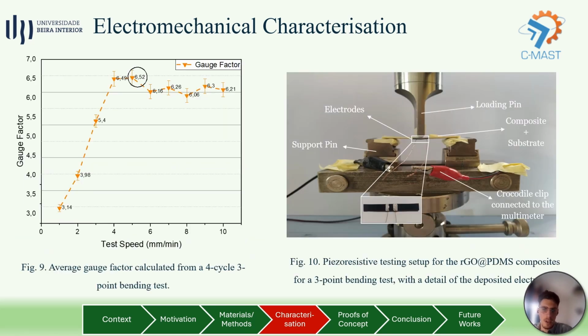We began with 3-point bending tests using the setup shown in Figure 10, and the first stage consisted of determining the best test speed, where a direct relationship with the gauge factor was observed, since speeds above 4 mm per minute always led to values above 6. However, at very high speeds, the electrical signal acquired by the multimeter was sacrificed due to its low sampling frequency, and so a test speed of 5 mm per minute was chosen.